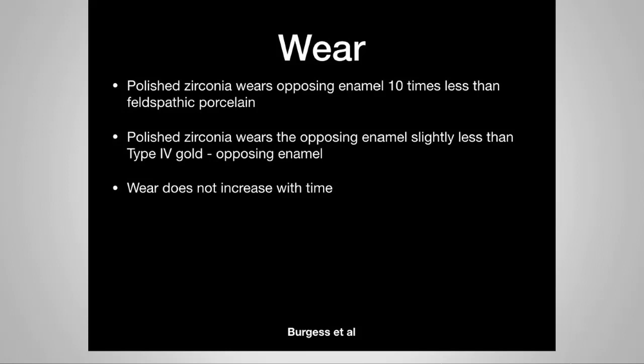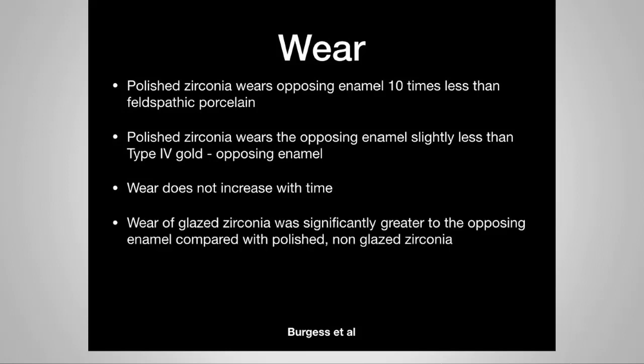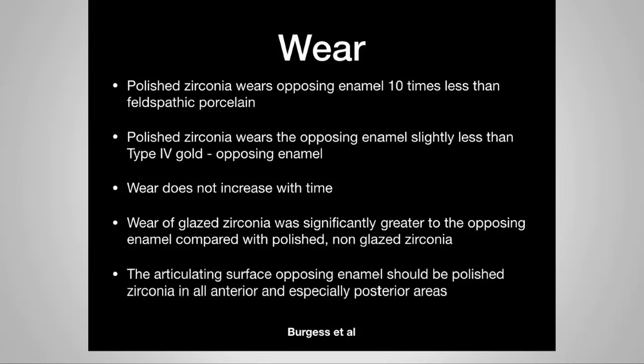Wear from zirconia does not increase with time. Wear of glazed zirconia was significantly greater to the opposing enamel compared with polished non-glazed zirconia. The articulating surface opposing enamel should be polished zirconia in all anterior and especially posterior areas.